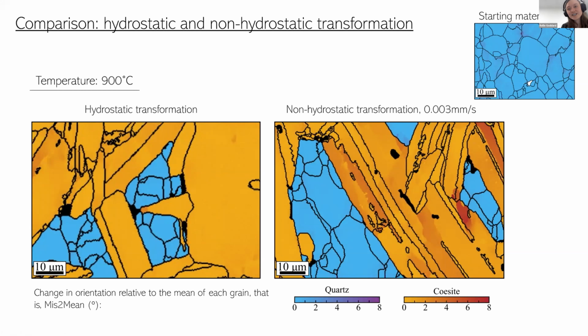And why this is interesting is twofold. Firstly, it's against what the theory predicts, and that's because coesite is the nucleating phase, so it's the one that's growing. And you'd expect if you're growing a phase into the quartz, you'd expect the quartz to be deformed as this new phase is nucleated. And secondly, it's because coesite is stronger than quartz under these conditions. So rather than deforming the weak quartz, we actually seem to be deforming the strong coesite. This is quite qualitative, so we want to do something a little bit more quantitative.